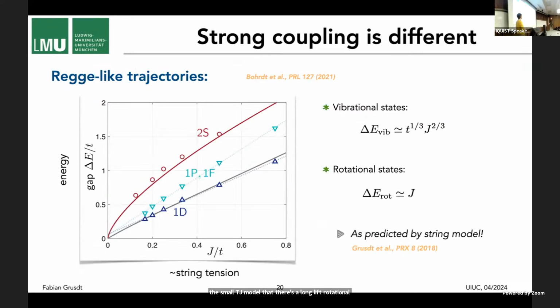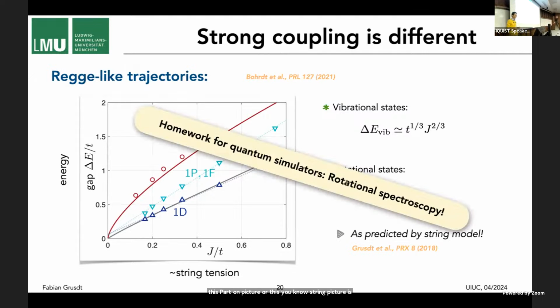Then you can ask, how does the string tension here, the J over t, relate to the energy gap of that first peak? It turns out these rotational states have linear relations here, whereas the vibrational peaks have this more curved form with this characteristic power law. Never mind the details, but the point is, by mapping out these dependencies, we can establish that there is such a linear confining potential, and this parton picture or string picture is very good in the sense that it qualitatively predicts these features. And of course, that's another homework for quantum simulation, to do spectroscopy and directly probe these rotational excitations, which they should, in principle, be able to do by using certain lattice modulations.